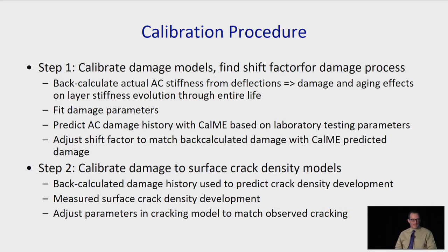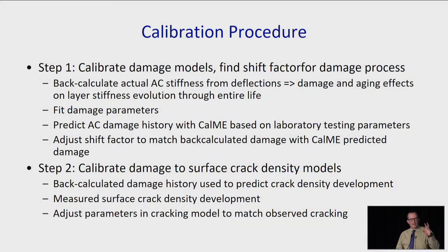Step one of the calibration procedure is to calibrate the damage models. Our basic approach is, if we can't predict the change in stiffness, then we don't really want to go to trying to predict cracking from stiffness. So we calibrate the damage models using back-calculated actual AC stiffnesses from the test sections. That gives us our damage and aging effects, comparing in the wheel path versus deflections taken to the side that only have the aging part going, fit the damage parameters, and then compare those. The basic parameters, like Harold was saying, are developed from laboratory testing, and then we adjust those for the damage process, and then we have a separate shift factor to take us from damage to cracking, which is the second part.